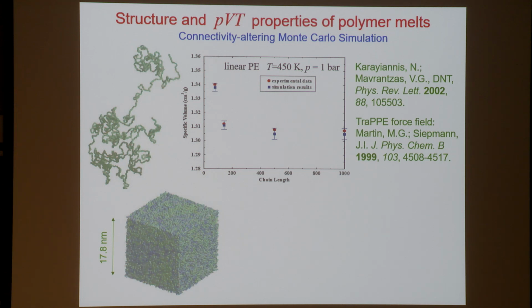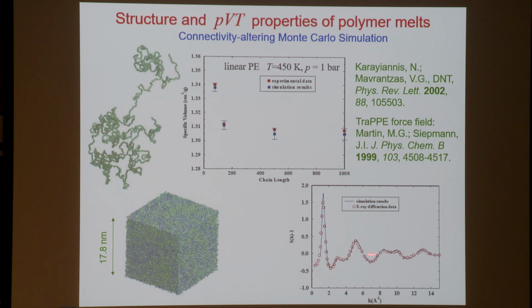volumetric properties. Here we see the specific volume, the inverse density, as a function of chain length for the homologous series of polyethylenes under these conditions, and we see a hyperbolic dependence as is experimentally observed. And we can also predict the packing of molecules in three-dimensional space. For example, this is a static structure factor, as one obtains by X-ray diffraction, and it exhibits a first peak, the amorphous halo, that is mainly of intermolecular origin, of correlations between carbon atoms on different chains, and some subsequent peaks at higher K values, which are mainly due to the bonding along the chains. And both are represented quite well in comparison with experiment.